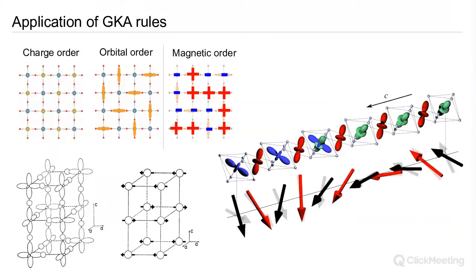But if we go back to these examples that I gave at the start, they do work. So we've got a charge order in this 50% system. This leads to this orbital order. And then what we can see is that when we have an occupied magnetic orbital, the dz squared minus r squared pointing towards a non-magnetic orbital, we have a ferromagnetic exchange interaction. And when we have essentially what will be a T2G facing a T2G, we have an antiferromagnetic exchange interaction. So it well explains this correlation between the orbital order and the magnetic order.